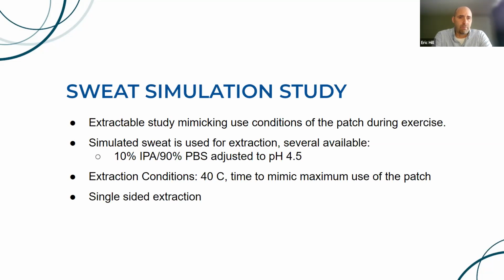In this case, you usually would extract at 40 degrees C. That's going to, again, mimic temperatures that you'd see at the dermal layer during exercise use or extreme use when sweat is being formed. And we're going to want to try to target a single-sided extraction, because again, this is a sweat simulation study. So in the controlled extraction study, we're trying to target extracting the individual materials so we get individual extractables profiles of each of the materials in the patch. In this case, we want an overall profile of the patch that simulates use. And so if we can, we want to try to do what's called a single-sided extraction. We want to only extract the side of the patch that contacts the dermal layer, not the outside of the patch that doesn't really have direct contact with the dermal layer.